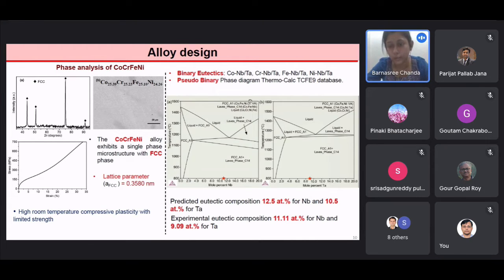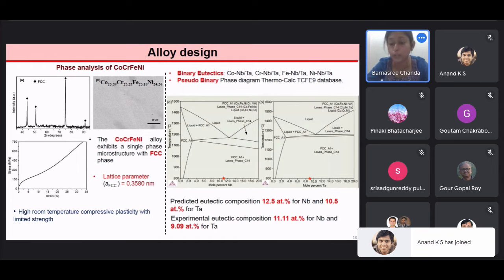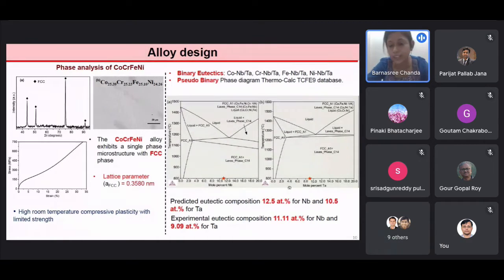So we developed the pseudo-binary phase diagram, and from that we see that the predicted eutectic composition lies at 12.5 atomic percent and 10.5 atomic percent for niobium and tantalum respectively. But after experimental trial and error, we got the eutectic composition at 11.11 atomic percent for niobium and 9.09 atomic percent for tantalum. Also, the predicted phases are FCC and Laves phase.